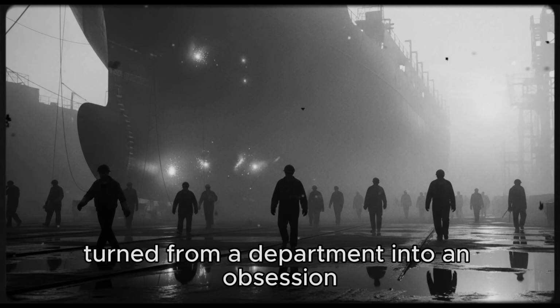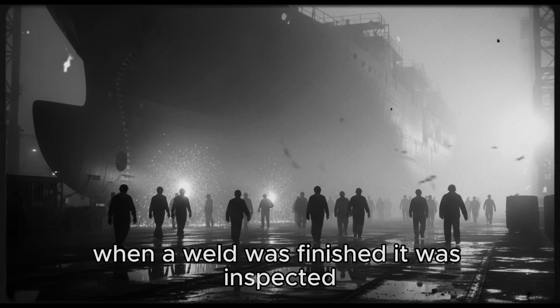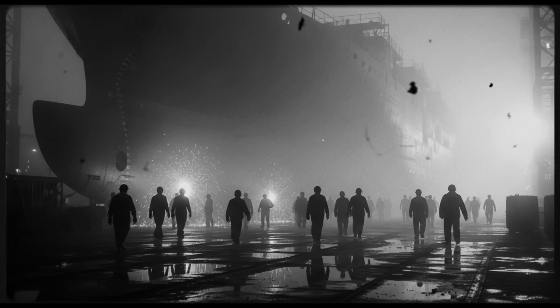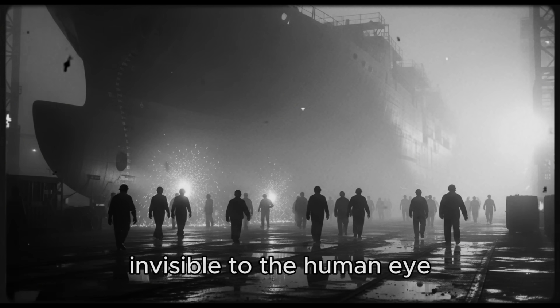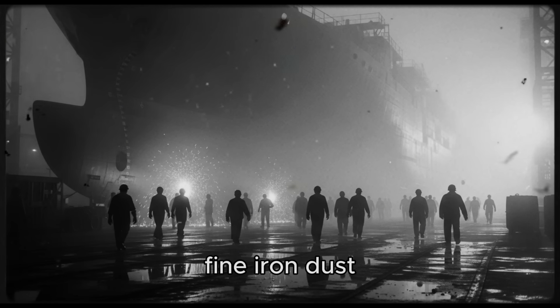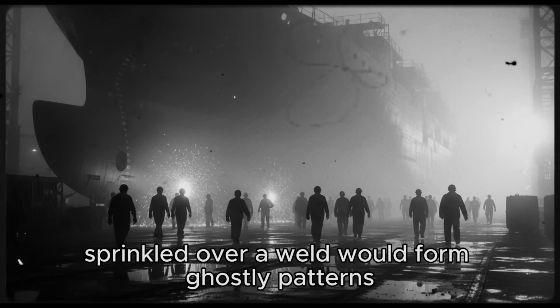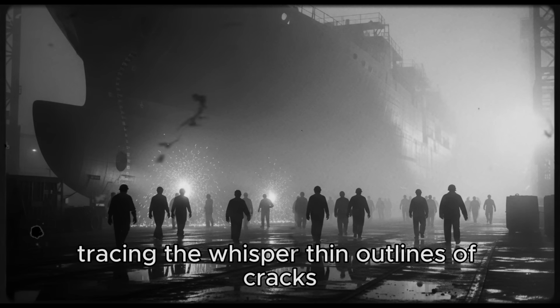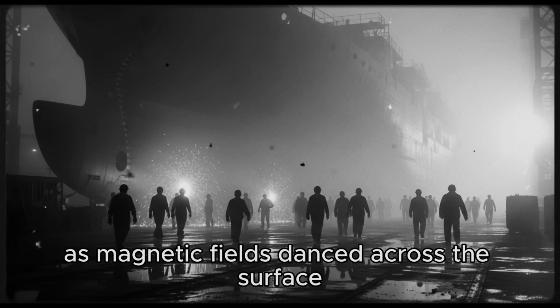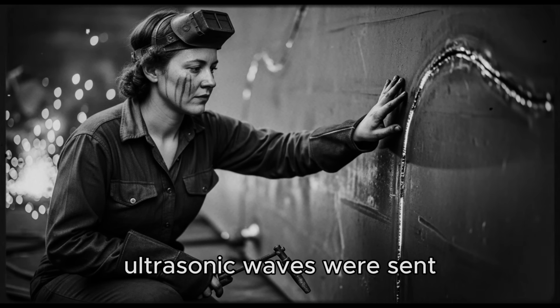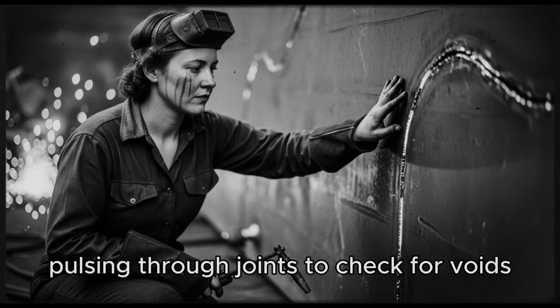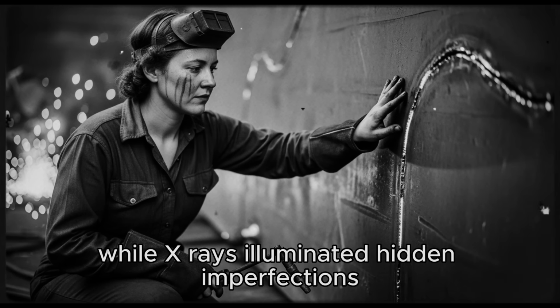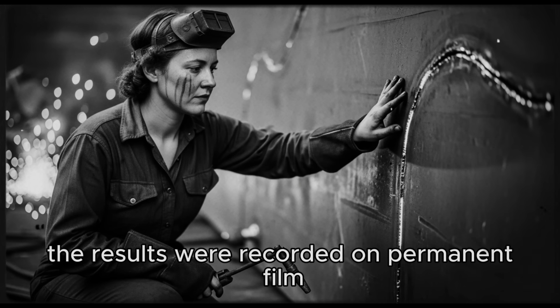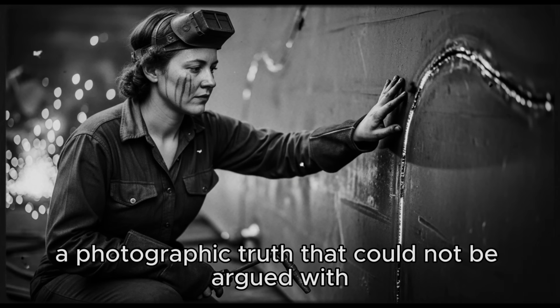Quality control turned from a department into an obsession. When a weld was finished, it wasn't simply inspected, it was interrogated. Magnetic particle testing revealed flaws invisible to the human eye. Fine iron dust sprinkled over a weld would form ghostly patterns, tracing the whisper-thin outlines of cracks as magnetic fields danced across the surface. Ultrasonic waves were sent pulsing through joints to check for voids, while X-rays illuminated hidden imperfections in the deepest seams. The results were recorded on permanent film, a photographic truth that could not be argued with.